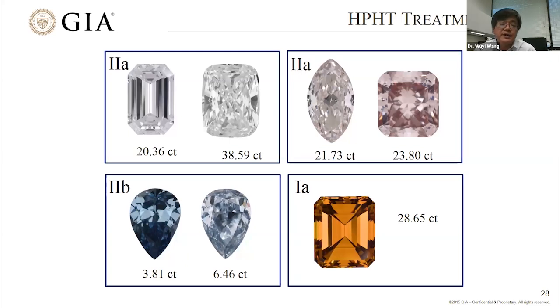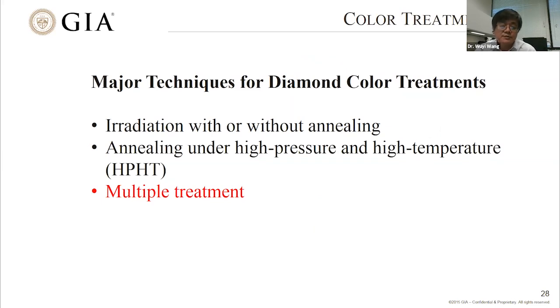So we talked about the irradiation treatment and HPHT treatment. The HPHT technology has a huge advantage over irradiation in that this technology can remove some color that we don't like. That is very different from irradiation. Irradiation doesn't remove pre-existing color, but HPHT treatment can, though that is very limited. It removes a brown color, and also the final result heavily relies upon the starting material chemistry. So both technologies have some limitations.